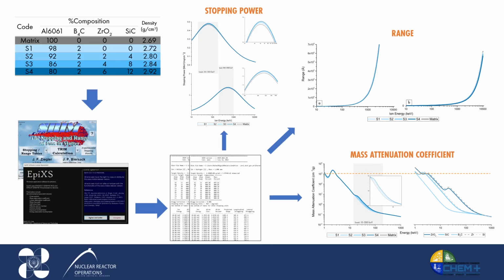In conclusion, the calculations conducted at different reinforced aluminum 6061 components showed that even in the maximum added reinforcements of 2% boron carbide, 6% zirconium oxide, and 12% silicon carbide, there is no significant improvement in their interaction with radiation. Thus, it has a low alpha, proton, and photon interactions in high energy regions. It is recommended that neutron interaction should also be investigated in further studies. In addition, the reinforced aluminum 6061 composite can be a possible candidate for suitable nuclear support structure material.